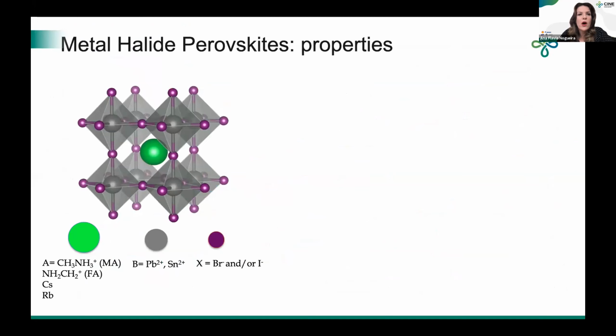Let me tell you more about this special type of perovskite, because perovskite is a chemical, is a structure, many oxides have these perovskite structures, but this kind of perovskite for solar applications or even light emitting applications is very special. You can see here that on the A side of this cubic perovskite, you can have organic and inorganic cations, and this makes a lot of difference. The composition of these perovskites for solar cells are really, really special. You can also see that for the B side, we have a cation that in most of the cases are lead, and X can be halide, bromide, or iodide.